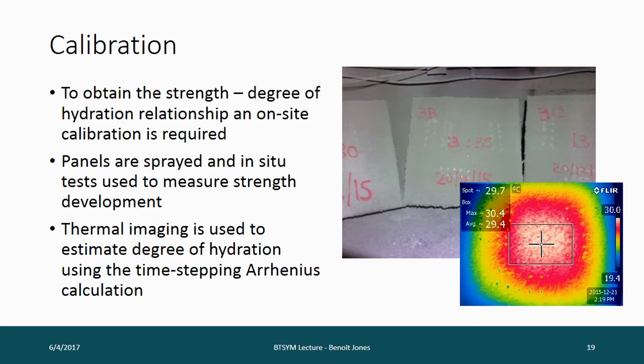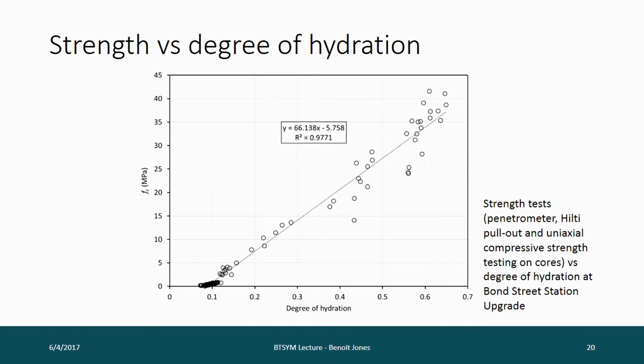So we have to actually spray at full scale into panels. What we do is we spray some panels, we do in situ tests, and we also do thermal imaging, and we plot the strength against the degree of hydration, and we get a linear relationship. So now we've got all the parameters we need for our software, and we can plug them all in, and then from a temperature history, we can say what the strength is.